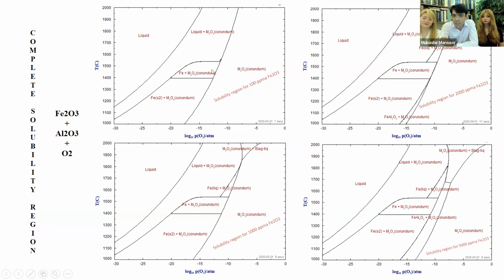If we go to the left into these boundaries which say iron plus corundum, or anywhere on the left of this line, then we would have tiny crystals of iron appearing in our crystal, or tiny crystals of hercynite, an iron spinel, appearing in our crystal, which is extremely detrimental to the appearance of those sapphires. So that means we should go down in the oxygen concentration, but not so much that we actually create precipitation of the iron in the crystal.